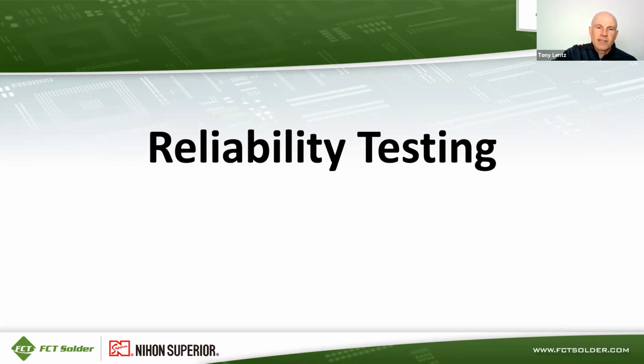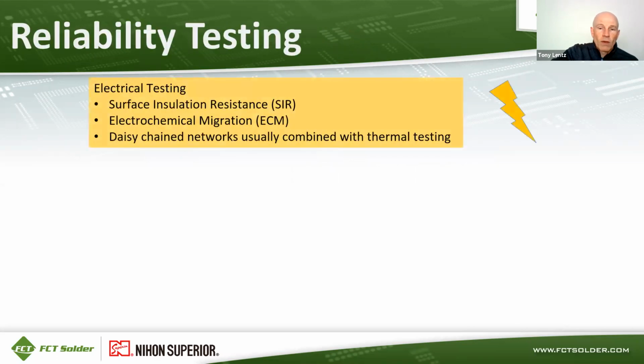So how do we do reliability testing? Some of the options for reliability testing are electrical in nature. For example, surface insulation resistance and electrochemical migration are common tests that are used mainly to test flux materials or solder masks, conformal coatings, those sorts of things to make sure that they are electrically non-conductive, and they don't grow dendrites, or there's no corrosion caused during the course of those tests. Typically, though, daisy chain testing is used in combination with thermal testing, which is an electrical test, where the electronics will be monitoring for resistance increase over time or electrical opens, which indicate that solder joints may have cracked.